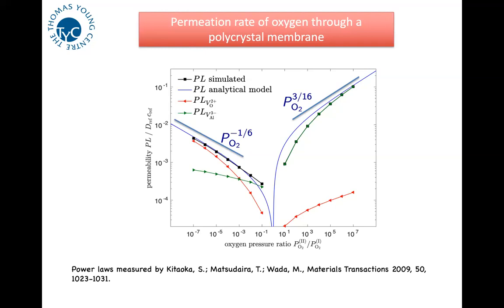And for high chemical potentials of oxygen, you're actually killing all the oxygen vacancies, so the diffusion is by aluminium vacancies. And so the diffusion rate goes down with concentration. That's the left hand of the graph. It goes down with partial pressure of oxygen rather, and that with that power law, that's experimental -1/6. And then when the oxygen pressure is much lower, then oxygen vacancies start to dominate, and then the diffusion rate goes up with the partial pressure of oxygen. Sorry, yes. So did I say oxygen vacancy is dominant? I meant aluminium vacancy is dominant. So Marcus's model then reproduced those two power laws in the asymptotic limits, as you can see there, his computations at other points.